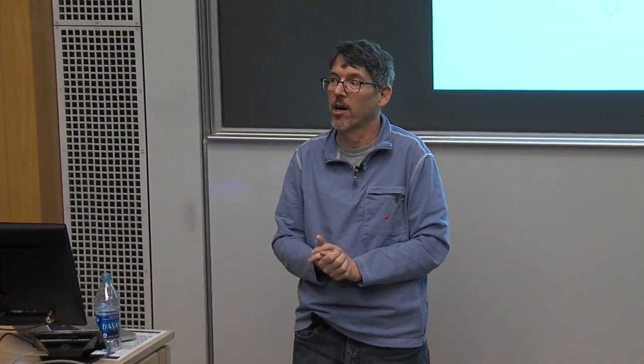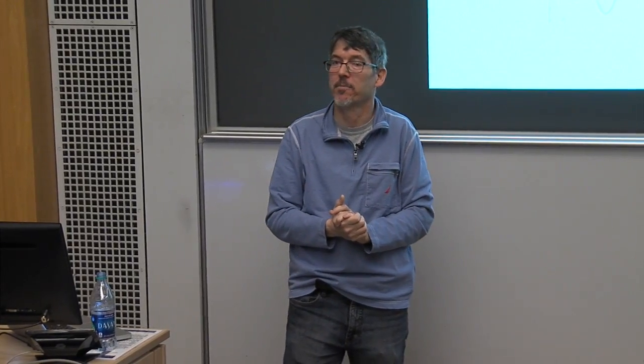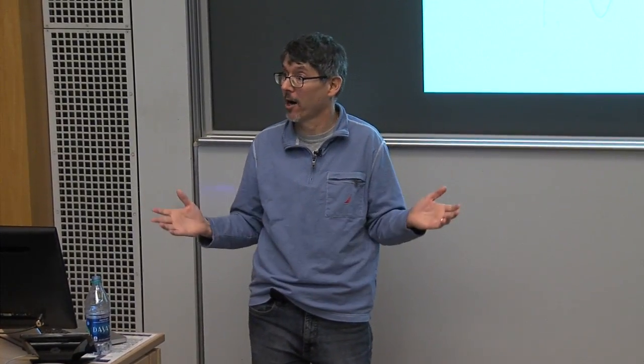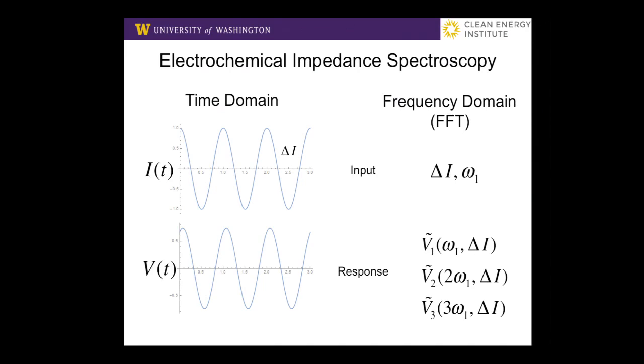So what our approach is to do electrochemical impedance spectroscopy. And the linear response of the system is widely studied for a long time. But what we're looking at then is perturbing the battery with a modulated current of some amplitude, delta I, as a function of time, and measuring out the voltage response. We Fourier transform it. We get out, well, the input parameters, the magnitude of the perturbation, delta I, the frequency of the input perturbation, omega 1, and out will come the complex Fourier coefficients, which will be related to impedances, right? The V1 will be related to the standard linear impedance.